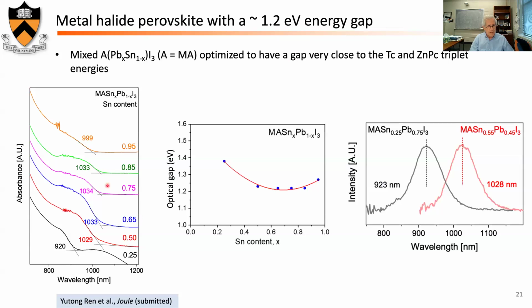So for this, of course, we needed, given that our singlet fission material is still tetracene and produces the same triplets with energy of 1.25 electron volt or so, a perovskite with a band gap slightly lower than the triplet energy if we had any chance to move the triplet excitation into the perovskite.